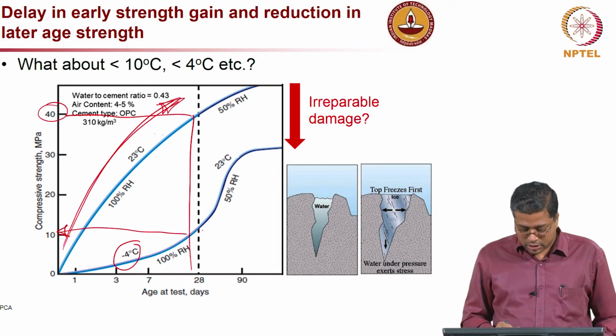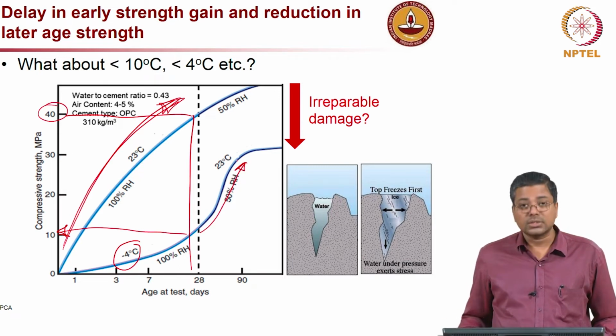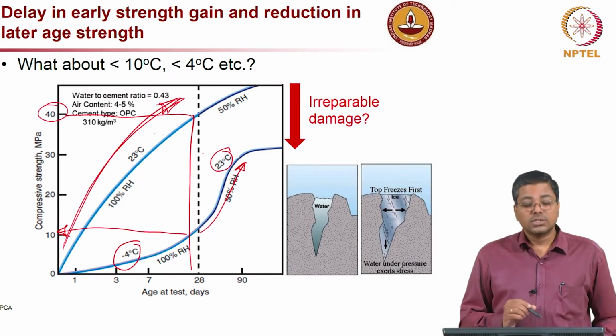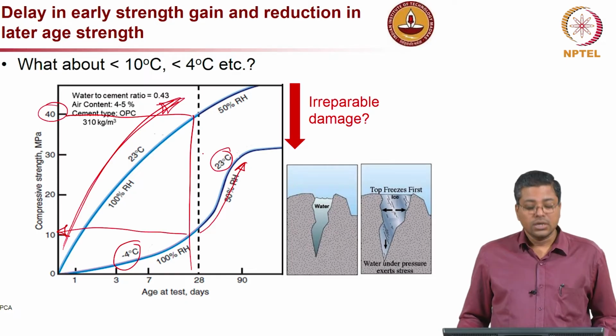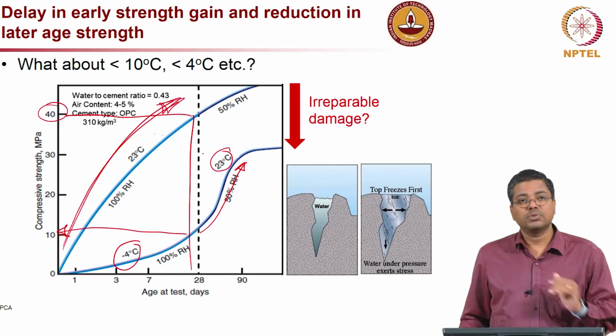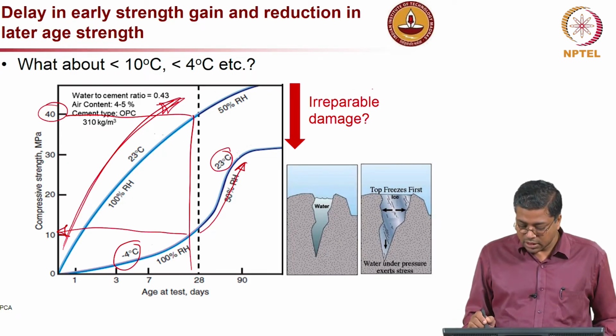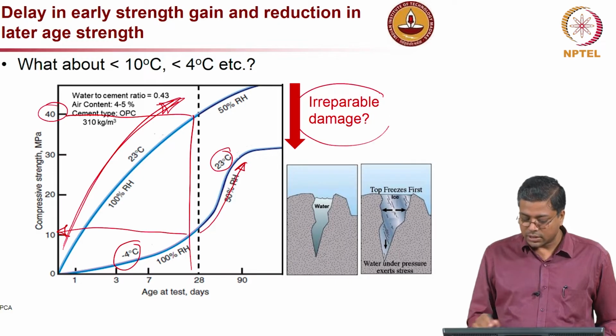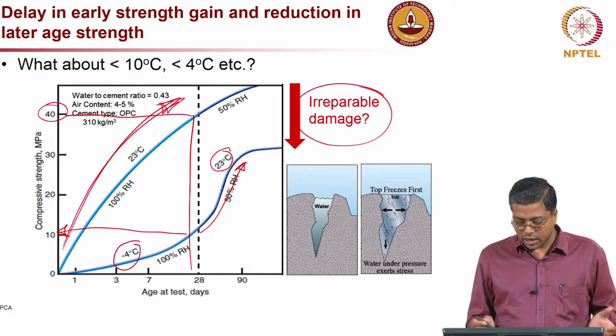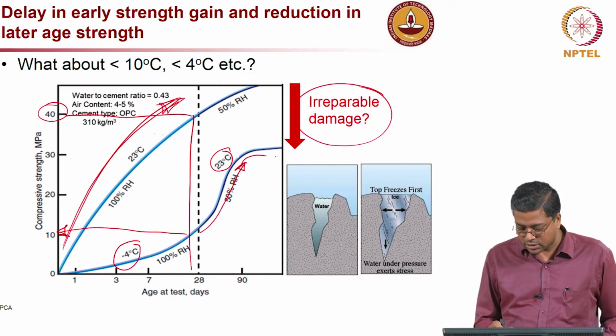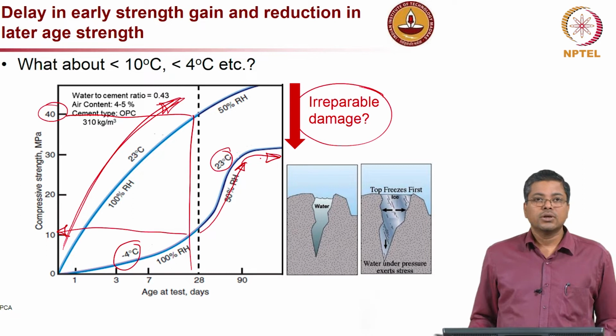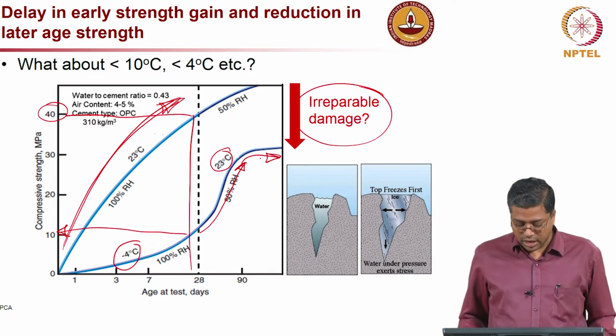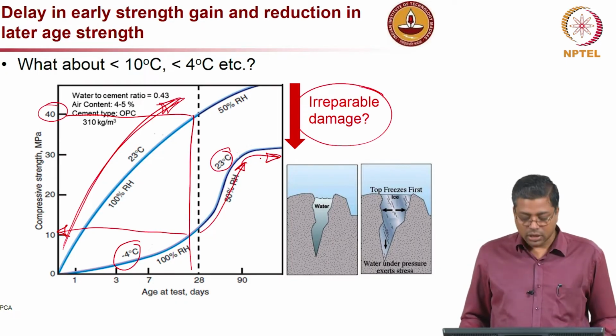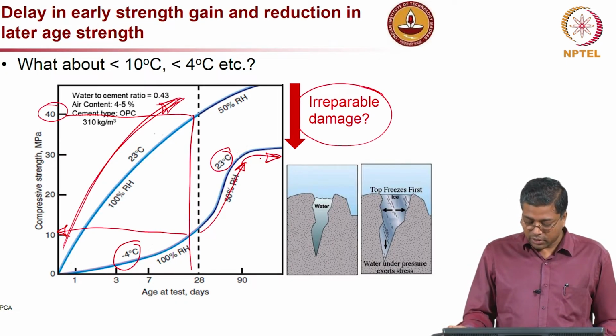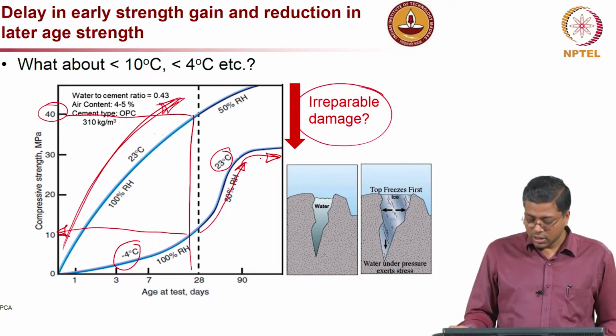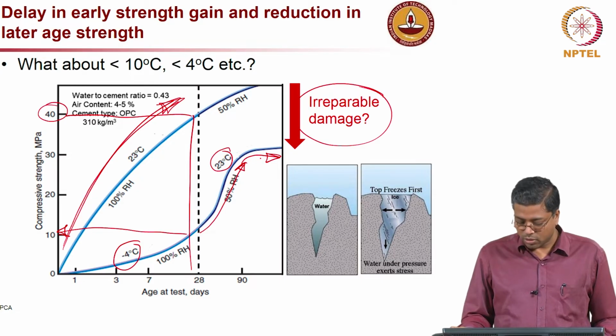And another important thing to notice here is, after that, when the temperature is maintained at about 23 degrees Celsius, still it is not able to reach the strength which the other concrete which was exposed to 23 degrees Celsius from the very beginning. So, there is a significant reduction in the strength, which I am going to call irreparable damage. So, that strength you cannot gain, because after about 90 days you can see the curve is almost flat. So, there is no significant strength gain after that. So, you have an irreparable damage when we are talking about very low temperature. So, this is something very important, and let us see in the future slides how to take care of these issues when you talk about cold climate.